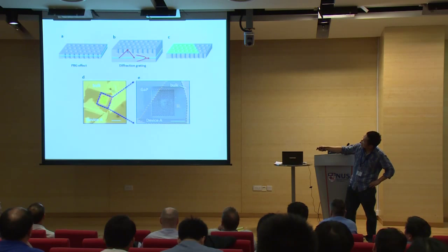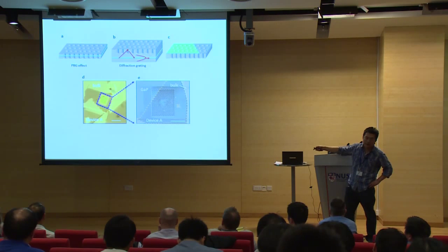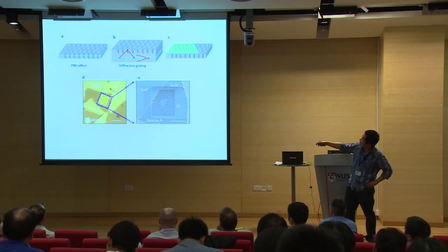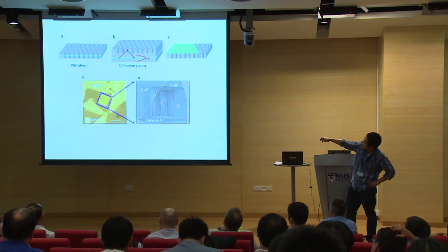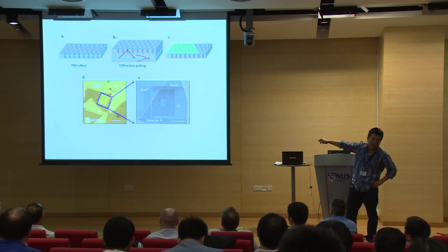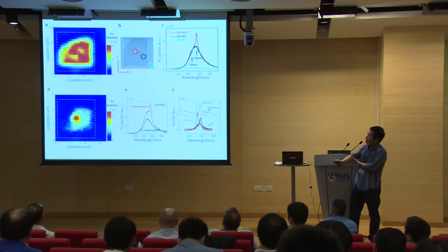So the bottom here is figure D, which shows the monolayer transfer. This is an optical microscope image. So the square in the middle is a photonic crystal with its cavity. And in the middle here, you can look at this SEM image of the monolayer tungsten selenide. The photonic crystal cavity actually is a defect cavity. An L3 cavity is in the middle. And then we look at these spatially resolved luminescence measurements.